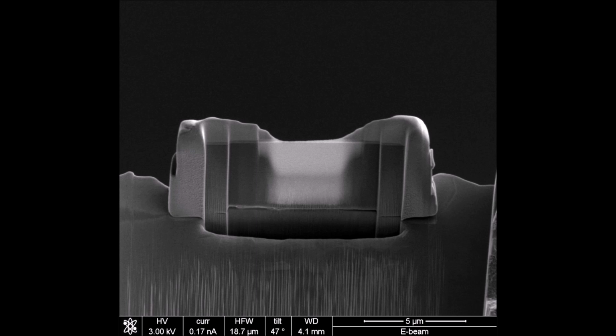But depending on your type of analysis, getting the sample as thin as you can possibly get it may not be necessary and may actually be counterproductive. So in the scenario we're looking at here, the idea that we want to get it as thin as we possibly can at the area that we want to analyze is definitely true, because we're talking about analyzing a thin film on the surface of a substrate.